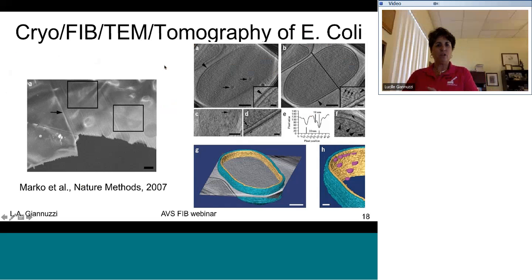Okay. Cryo-FIB TEM is possible. People are doing it more these days. It is non-trivial. It takes a lot of time, and you have to be really careful with all the cryo transfer steps. So you have to get a cryo sample into the FIB, do the FIB milling, and then cryo transfer it into a TEM holder and into a TEM. But nevertheless, it is possible to FIB mill on a cryo sample and do this work.